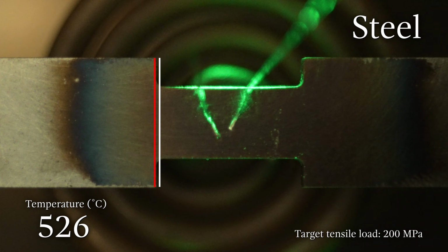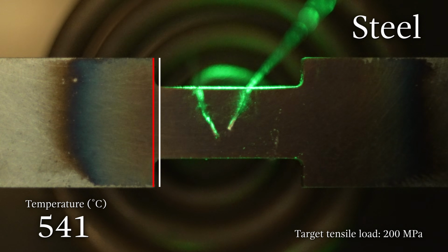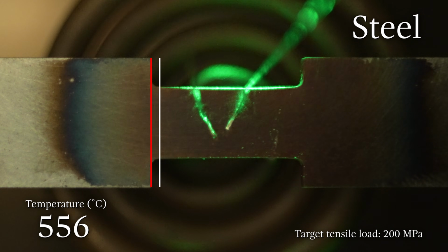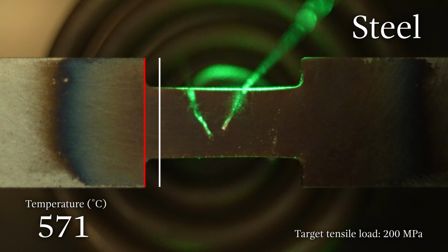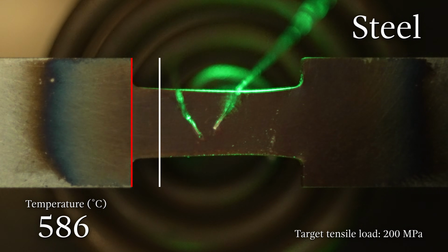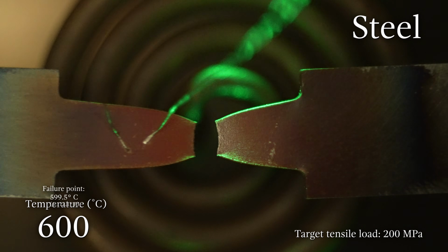Now the steel's strength drops so much that the slow, time-dependent creep gives way to rapid deformation. As it stretches, it rapidly decreases in cross-section, and eventually the remaining metal can no longer bear the load.